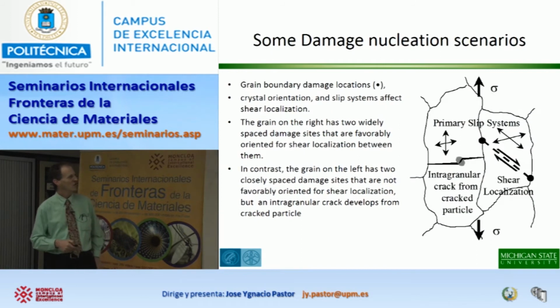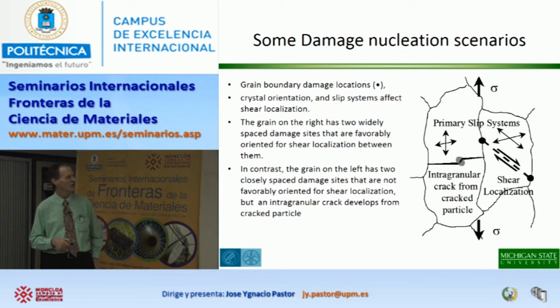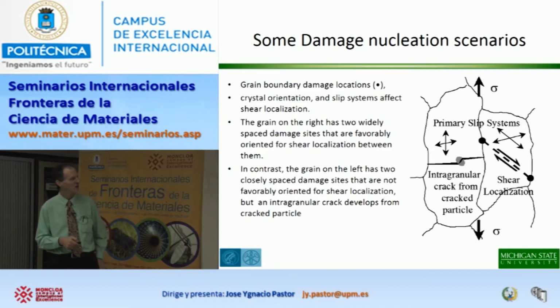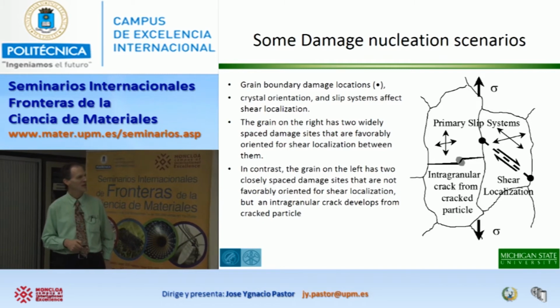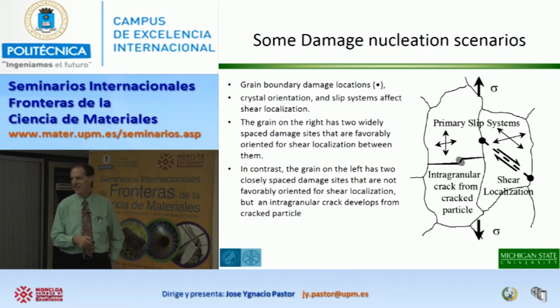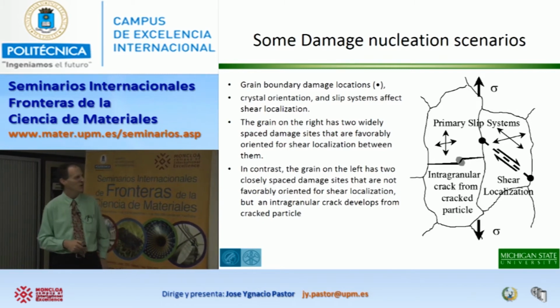So just to illustrate the point I just made, let's suppose I have a region of microstructure, and I have a damaged site at a grain boundary here, and another damaged site, whatever kind of damage you might want to imagine. Then if these two points of damage are linked together by a slip system that is highly activated, such as if I pull in tension, that's tilted in a way that I would expect a lot of stress or a lot of strain to take place, then I could essentially get damage to connect between these two locations.